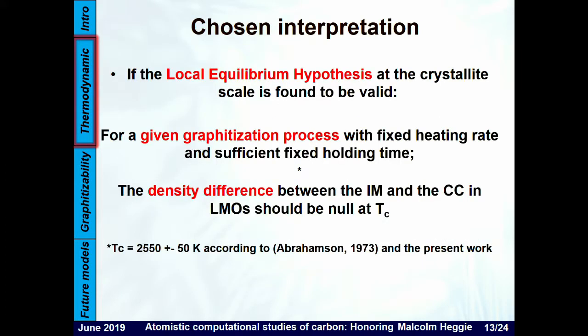So the interpretation is, if the local equilibrium hypothesis is valid at the scale of a crystallite, for a given graphitization process with fixed heating rate and fixed holding time, that is, you only try to model a single graphitization process with a single heat treatment time and a single value for the holding time at maximum temperature, then the null value for the surface energy should be interpreted as a null difference between the density of the intercrystalline matter (IM) and the crystalline core (CC). So basically, the two entities of the LMO merge together and become a single body at this temperature.